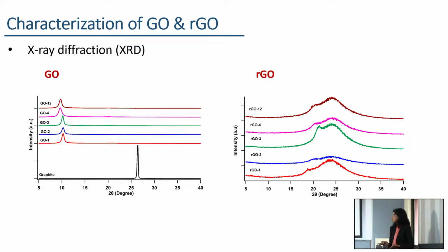Here I have shown the XRD spectra of graphene oxide as well as the reduced graphene oxide. Here I have shown the XRD spectra for graphite, which shows the sharp and intense symmetric peak at around 26 degrees, corresponding to the 002 plane of graphite. That shows the highly crystalline structure of this graphite.